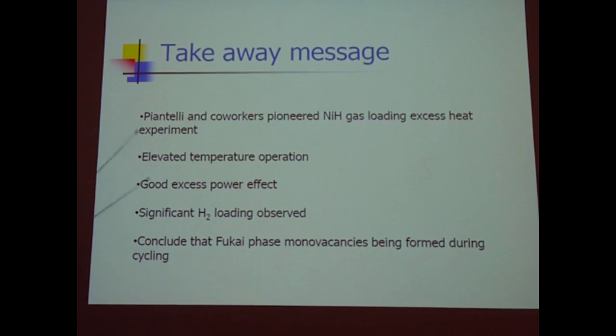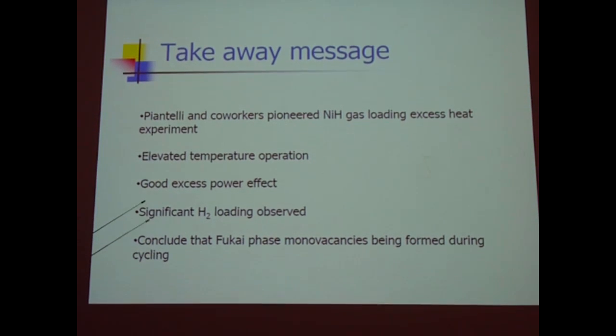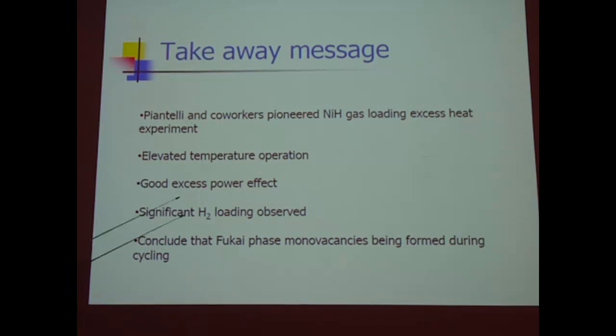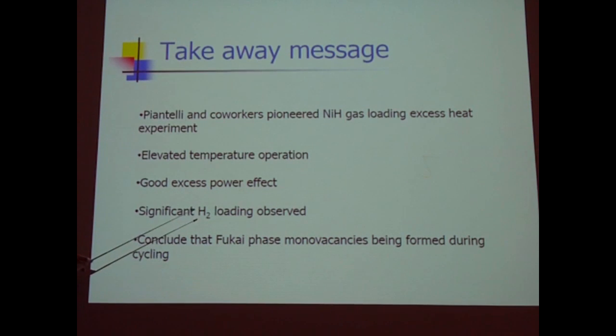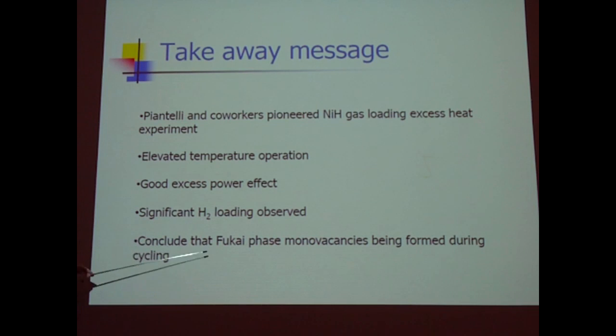Takeaway message. Piantelli and co-workers pioneered nickel gas loading, elevated temperature operation, good excess power, and we get H2 loading. And basically the conclusion I came to is the following. We'd argued earlier that when the H goes into the nickel, it segregates. You get little clumps of high loading. But they're operating at elevated temperature. At elevated temperature, they're high enough where the vacancy diffusion coefficient is high enough to actually do some good. So the thinking is that during their loading cycles, they're making Fukai phase. And the Fukai phase has defects, and the solubility is much higher, so it's giving places where the hydrogen can go. And that's why the loading is increasing.